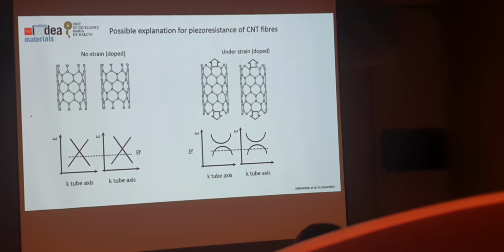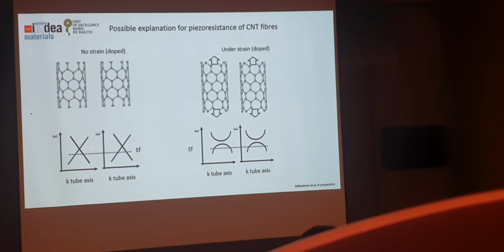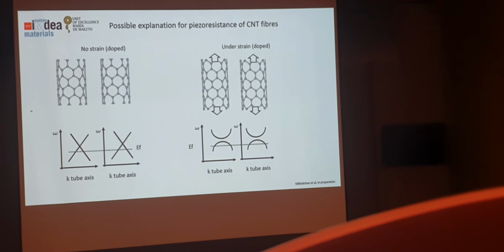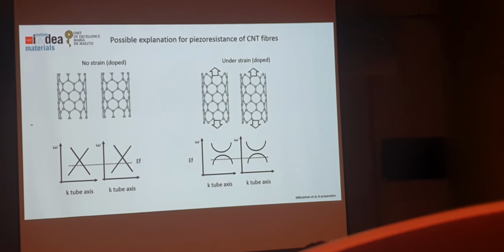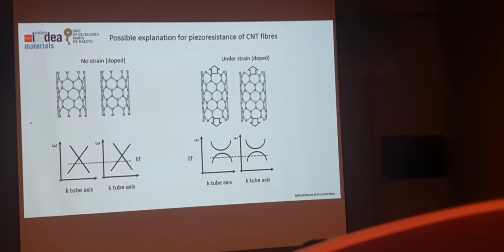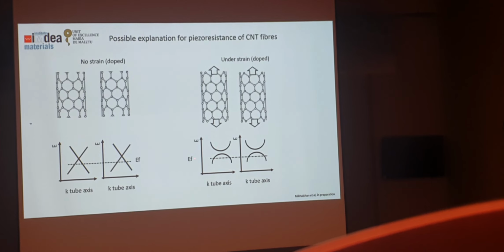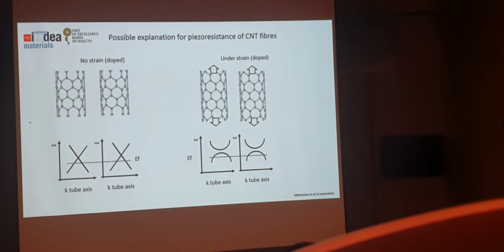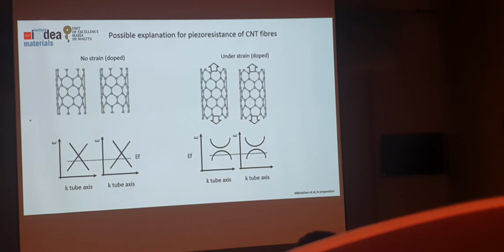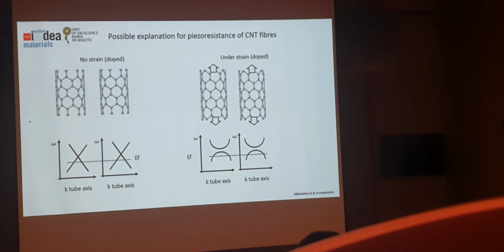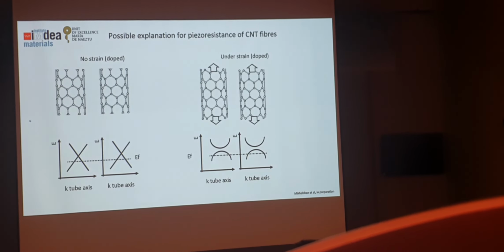In the case where the tubes are doped, where the Fermi level is pretty far, and therefore there's a high density of charges, even under strain there will still be tunneling because there's a high number of states that the electrons can tunnel through. So I think it's in the tunneling resistance that is the piezoresistive effect.